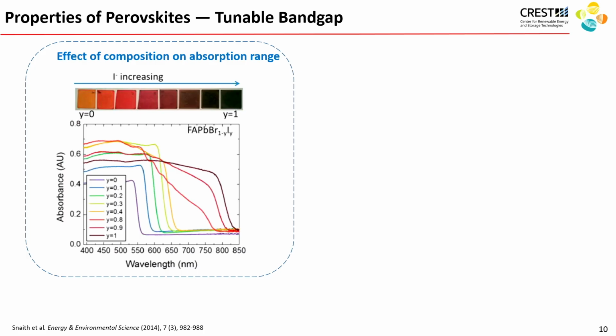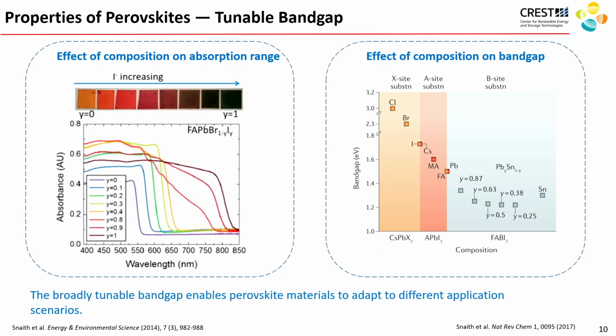By simply varying the halide composition, we could change the band gap of perovskites. That's what makes them very tunable and very useful as materials in solar cells, especially tandem solar cells, because we could tune the band gap very readily. So we have multiple levers for controlling the band gap, either by controlling the halide composition or the A-site composition. And in fact, also the B-site as well.